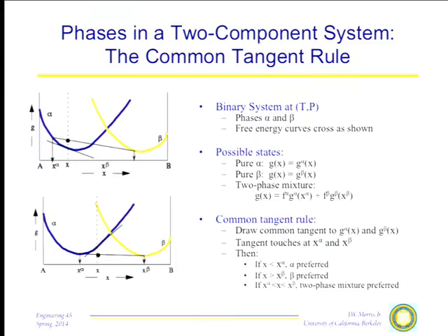Well, you might ask, does that ever occur? Yes, it does occur. There's a whole set of reactions. I'll briefly touch on them. The theory is a bit beyond this course, but there's a kind of chemical decomposition in solids called spinodal decomposition. And what happens in spinodal decomposition is you get into a regime where this curve turns over, so it's concave down. And if you can get your system into that regime, the alpha phase will want to spontaneously divide into two regions, both of which are alpha phase, but they have different compositions.